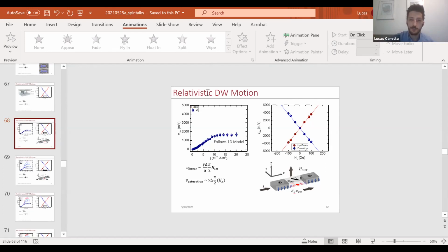So this bismuth-YIG is a perfect system in that it's extremely low damping, so there are no other dissipation mechanisms. There's no DMI, so you don't break Lorentz invariance in that sense, but we can still use a magnetic field to manipulate the domain wall how we want. So the short answer to your question is, yeah, there are other ways that you can probably get this sort of dynamics. You just have to be careful with how you introduce these new properties.